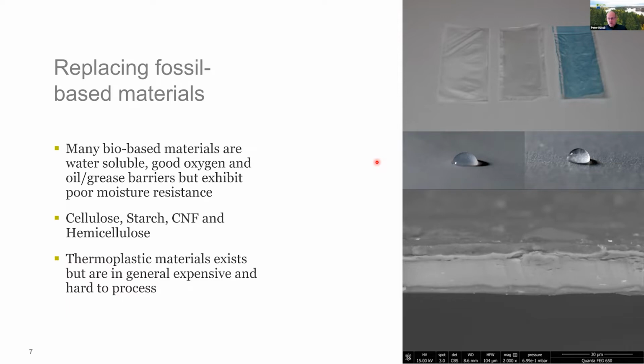The thing here is that we have quite a lot of bio-based materials that are quite good oxygen barriers, and they're water soluble, but they have quite bad moisture resistance. Nanocellulose is a typical example of this. These are actually nanocellulose films. If you just have the nanocellulose film, you can see that you have a quite hydrophilic surface, and this water drop will actually dissolve into the surface of the nanocellulose.